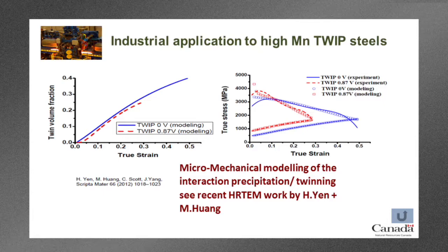And so these two graphs here are some of their first results, micromechanical modeling, showing the interaction of precipitation and twinning for a reference steel with no vanadium and the same steel with a high amount of vanadium added, 0.87 in this case. So what you can see is that when you add the vanadium, they do see quite a strong change, or a reasonably strong change, in the strain hardening behavior. Again, they do have parallel tensile behavior here. So the model is the points, and the experimental data is given in the line, the blue line and the red dotted line. And you can see the agreement is actually very good. So we think that we're actually improving our understanding of that phenomenon.